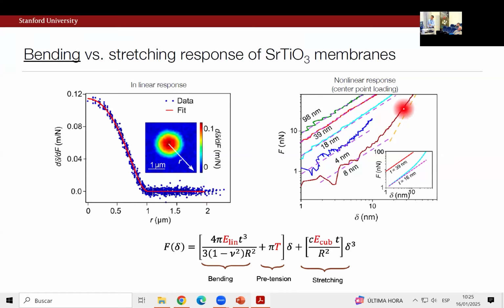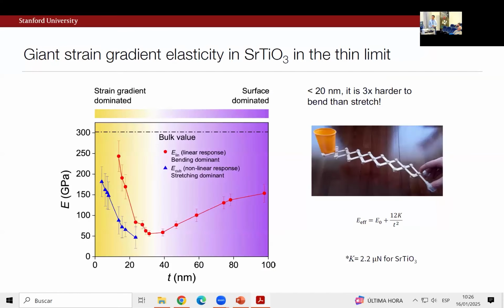So having done that, now if we look at poking a membrane, these are different membranes going from 100 nanometers thick to skinnier and skinnier. Of course, when it's thick, it's hard, within the limitations of your experiment or the cantilever forces you can apply. We're just in the linear regime and what we can access. But when we get skinnier and skinnier, you can see this crossover from linear to cubic term. Okay? And so that's the experimental way we can actually try to make the kind of experimental summaries that I'm about to show you. That's how we're going to extract all of these guys. Okay, so what did we find?